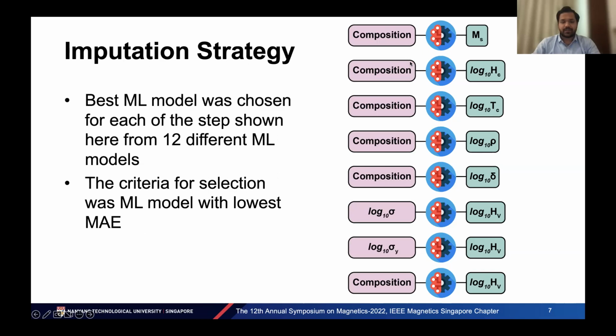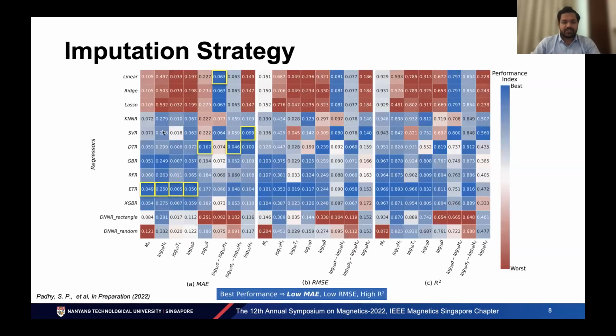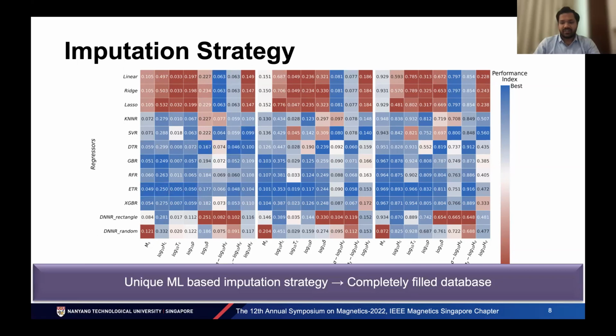Now, for each step, 12 different ML models were built, and the best model was chosen based on the lowest MAE. Now, let me show the results for this. If you can see in this chart of the performance of the models for various steps, the highlighted box indicates the models with the lowest MAE. These models were used to completely fill the database. After filling the database completely using this unique ML-based imputation strategy,